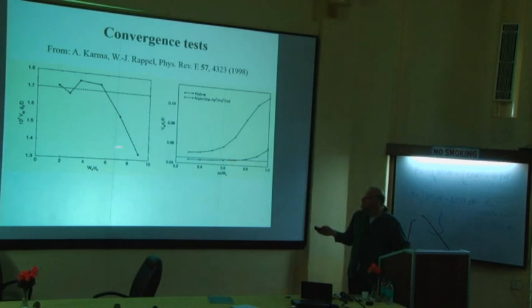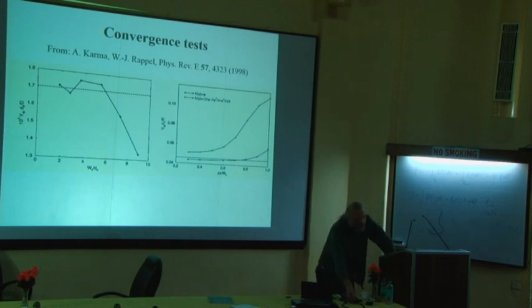So here they chose different members of that big family of models that can simulate the dendrite. And you see here, if the interface thickness is small enough, they get fairly consistent results. That is, they get approximately always the same velocity. If the interface thickness gets too big, well, then you get results that are off. And how can I judge if the interface thickness is too big?